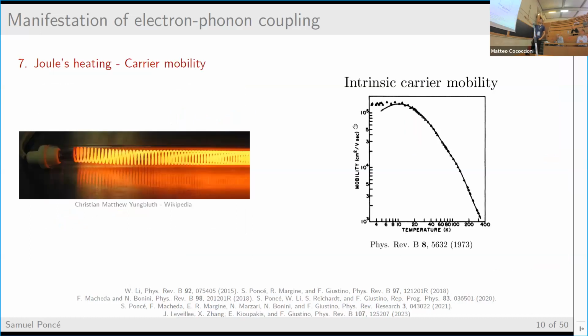And finally, the last manifestation that I want to talk about is mobility, or the transfer of electric charge. When you apply an external electric field, you will start to make the carriers move. This is Joule heating, and the velocity at which the carriers travel in the material will be reduced through the interaction with the lattice in which they are propagating. And if you increase the temperature, you're reducing that mobility, because you are increasing all the collisions with the lattice.